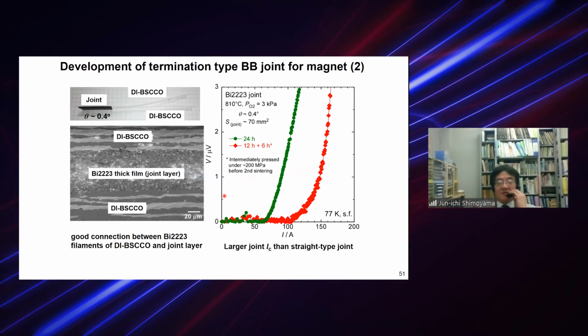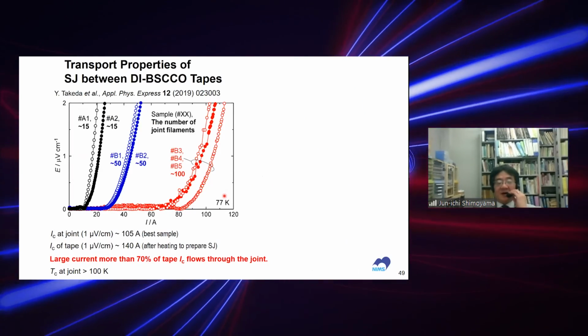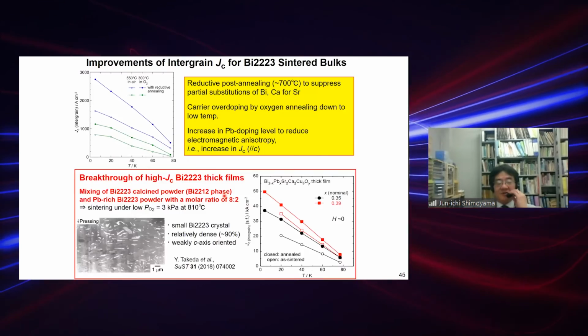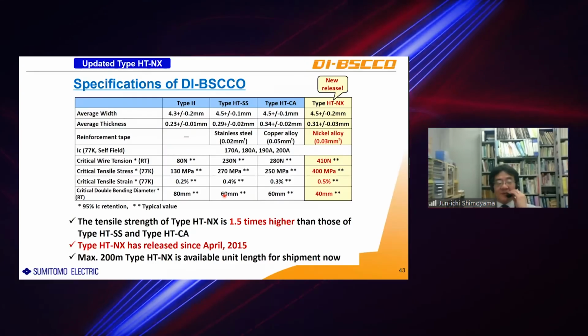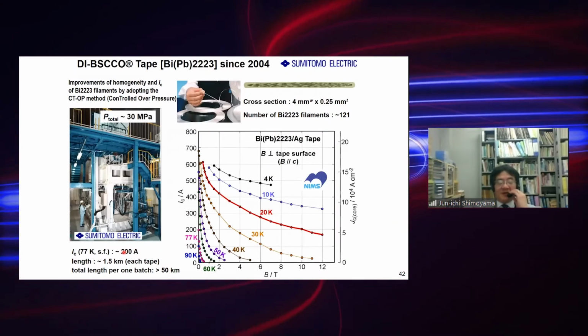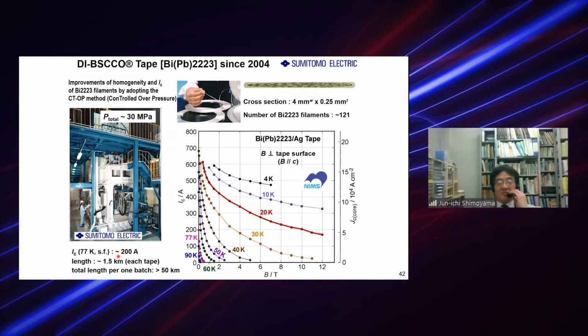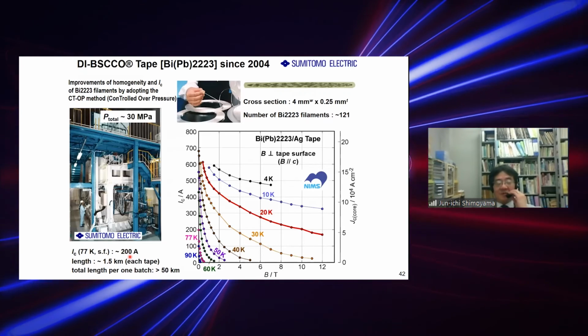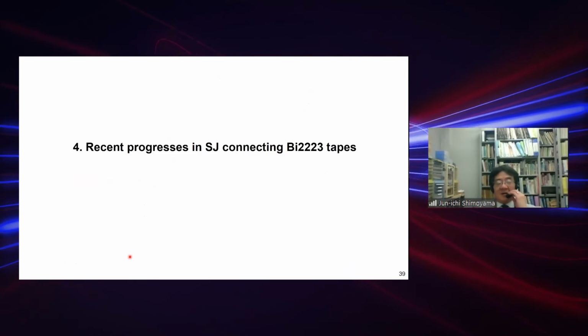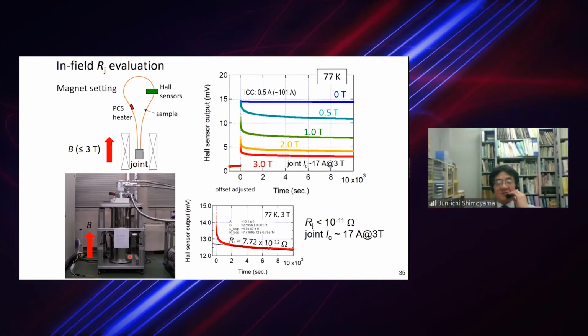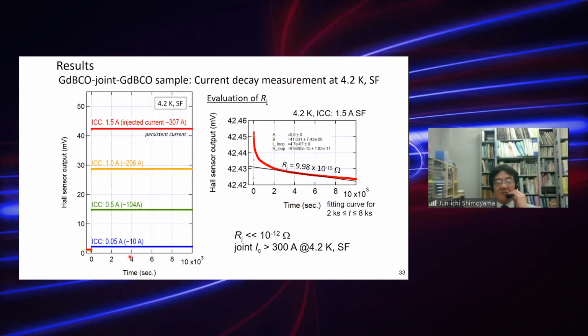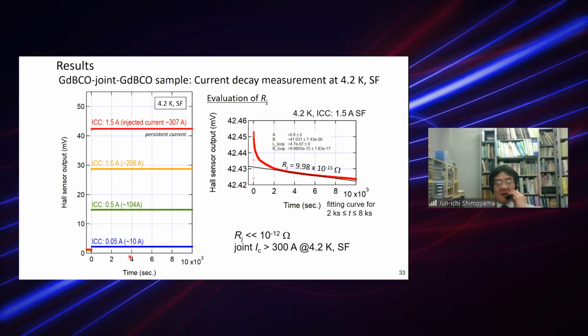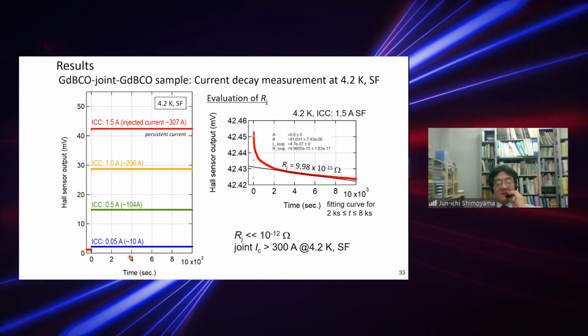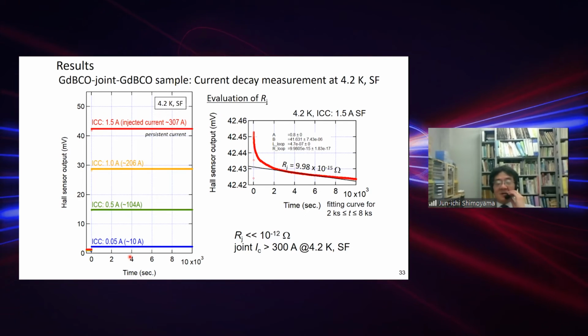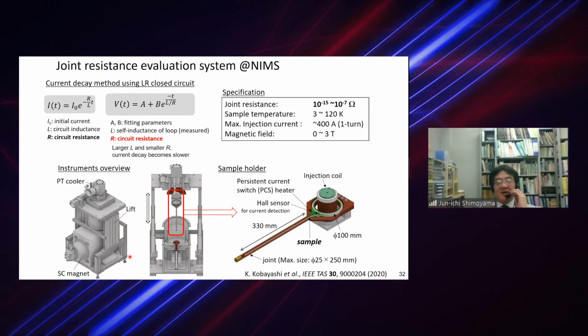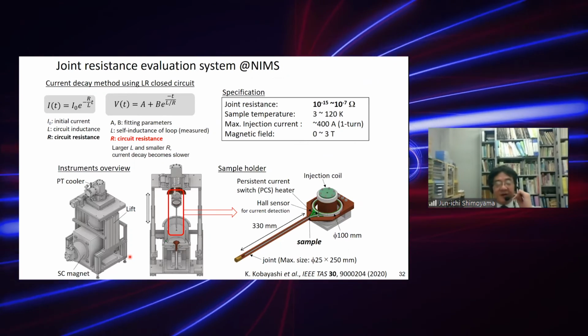For example, Bi-2223 tapes, which has an IC of around 200 amps before preparation of the joint. However, after preparation of joints, this value decreases down to 150 amps. In the case of the REBCO, it is more complicated. Essentially, such degradation should not occur in the REBCO system. However, introduction of oxygen is very important. So if oxidation is not sufficiently performed, superconducting properties of the REBCO tapes may degrade. It depends on the oxygen annealing conditions.